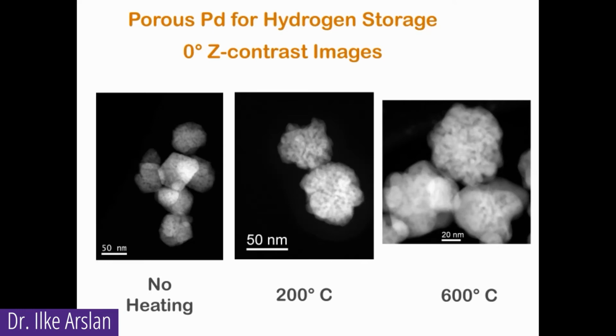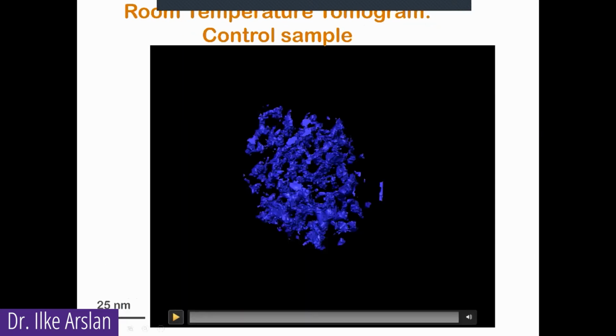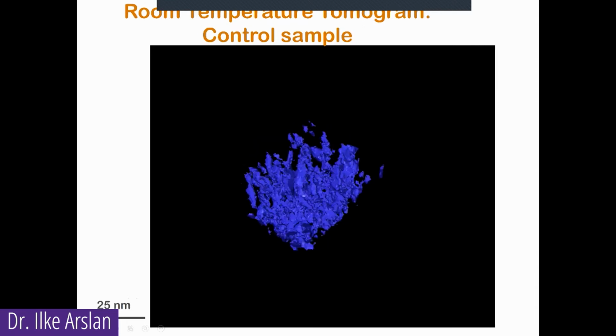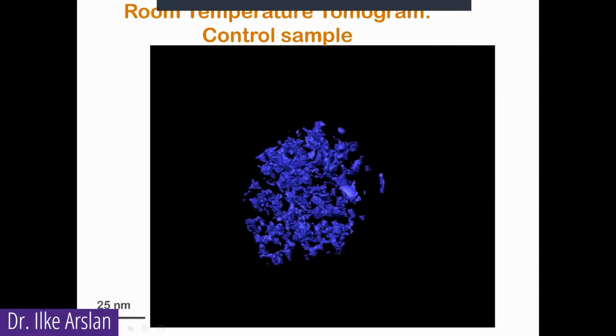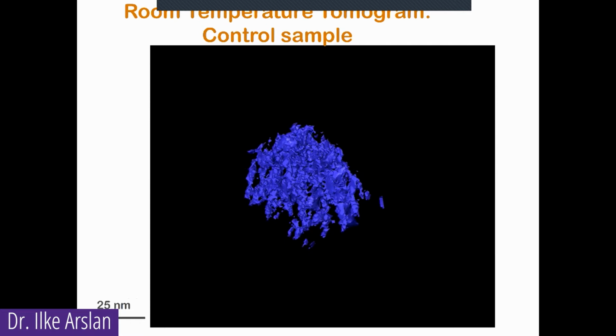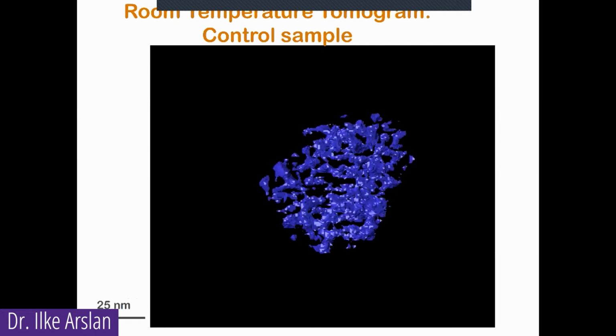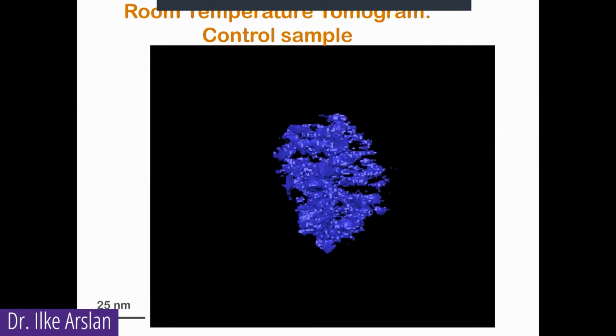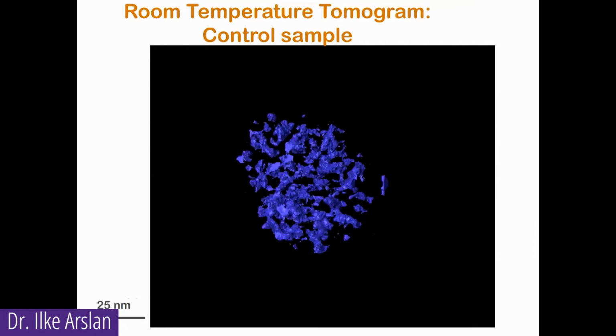So we studied them with different temperatures. We would heat it up and then cool it down to lock in the pore structure and then do tomography. And similarly, we would increase it until we would see that the pores would start breaking down. Now, this is a tomogram of the inverse. So what you're seeing here is actually the empty space, and what we're seeing is the pore structure. So we took away the palladium and you're looking at the pore structure.